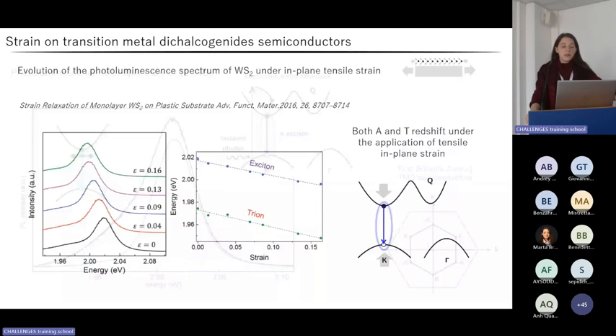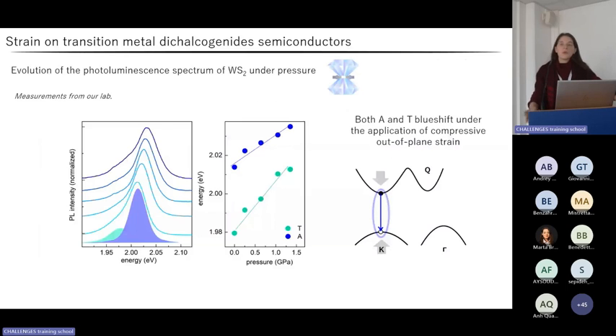As you can notice from the example reported over here, under the application of in-plane tensile strain, the A exciton band of monolayer tungsten disulfide redshifts, indicating a progressive reduction in the direct band gap energy at the K point of the first Brillouin zone. Conversely, when we apply high pressure, we notice a blueshift in the A exciton band, which is associated with an increase in the energy of the direct band gap.